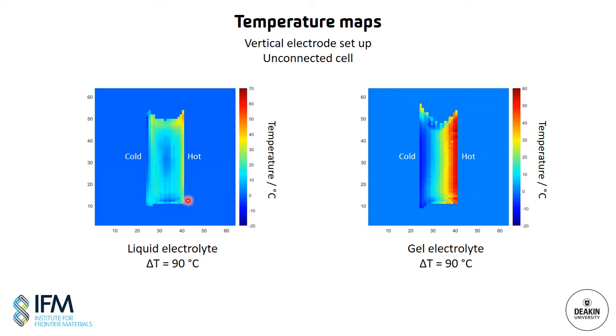So then knowing the temperature of the electrolyte as a function of space is essential to later on generate the concentration maps of the redox species in the working connected cell. The temperature difference between the hot and cold electrolytes in these images is 90 degrees in both cases. On the left we can see a more or less uniform temperature across most of the electrolyte, with colder and hotter regions visible at the electrode surfaces. This is obviously due to thermal convection that rapidly circulates the bulk of the electrolyte, and you can actually see a cooler kind of stagnant area in the center. For the gel electrolyte, the convection is prevented by the polymer matrix, so what we end up with is a linear temperature gradient between the two electrodes.